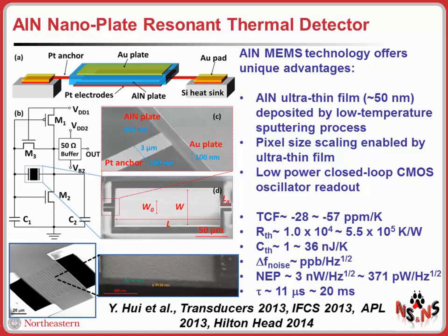Given the small dimension of this device and some other tricks that I'll describe later, we can achieve very high thermal isolation, so two orders of magnitude improvement in thermal isolation compared to other demonstrations. These devices are characterized by a very small thermal capacitance since they are very tiny, and still they have very good noise performance because, as I will show you later, despite this scaling, we can still maintain good high quality factors. So we demonstrated noise equivalent power as low as a few hundreds of picowatts per square root of hertz, with a thermal time constant ranging between 11 microseconds and 20 milliseconds, depending on the particular design.